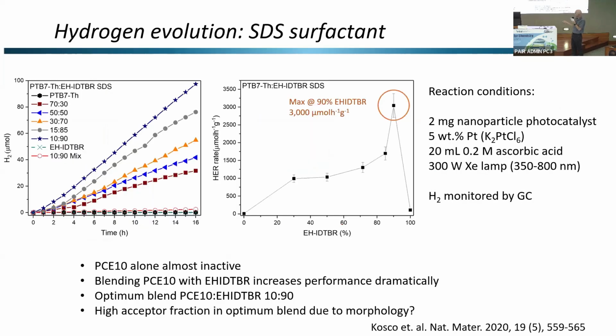And in fact, when we look at the hydrogen evolution, it's actually pretty good, the mixture. But we can see here, the maximum is at a ratio of about 90% of the acceptor and only 10% of the donor. So that's not a very good situation for efficient exciton splitting of both donor and acceptor.